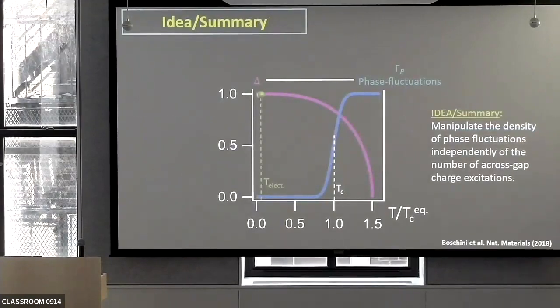Can we disentangle these two effects? Based on temperature it has been particularly challenging because everything changes. So the idea was the following. Here you have two quantities of interest. One is pairing and the other one is phase fluctuations, so fluctuations of that phase coherence. And Tc is usually defined not only when the pairing is finite, but also when a certain value of phase coherence is reached, at least on the underdoped side. So is it possible to do an experiment where you come in with a pump, you excite your system, and now you look at what happens?